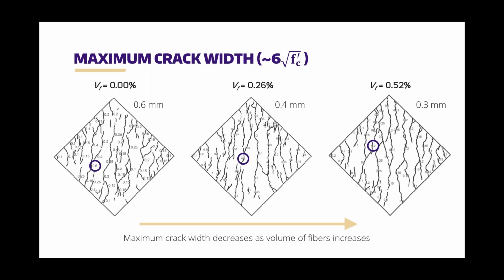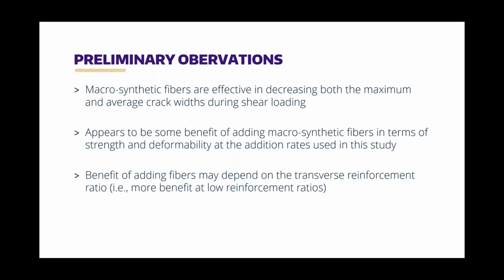And you can see we're comparing 3 different volume fractions from 0% to 0.52. And the maximum crack width, again, decreases as the volume of fibers increases. So that's exactly what we hoped for, and that's what we saw as well. So that's good news there.